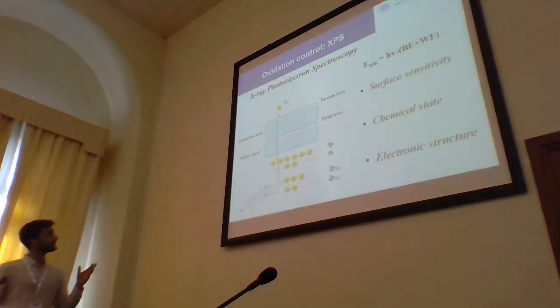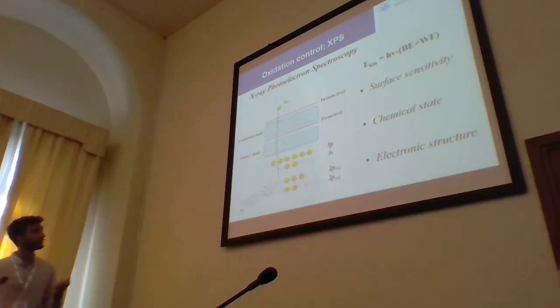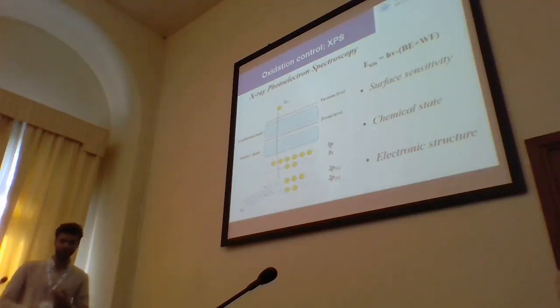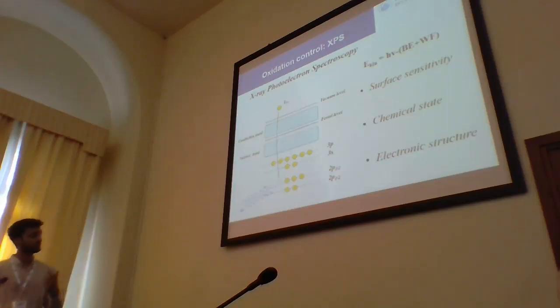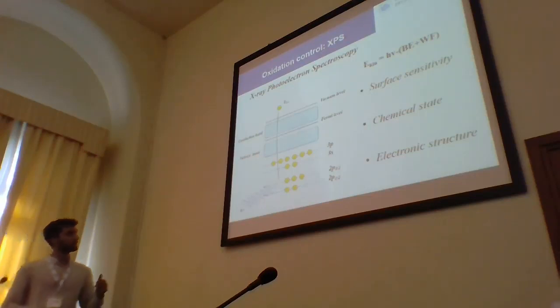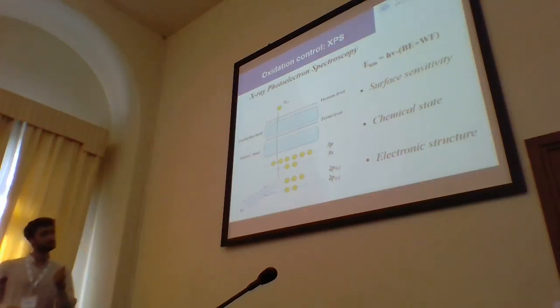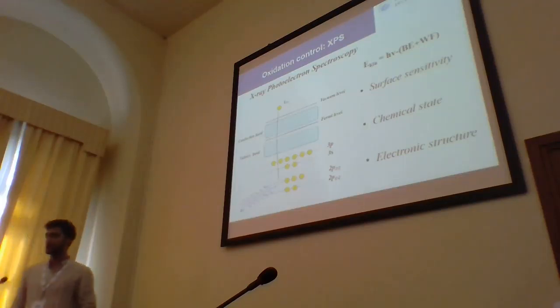So we can record the kinetic energy of this electron, which depends on the energy of the photon beam and on the binding energy which it had inside the solid, of course, and also on the work function. So this technique is surface sensitive and, most importantly, gives us information about the chemical state of our sample.